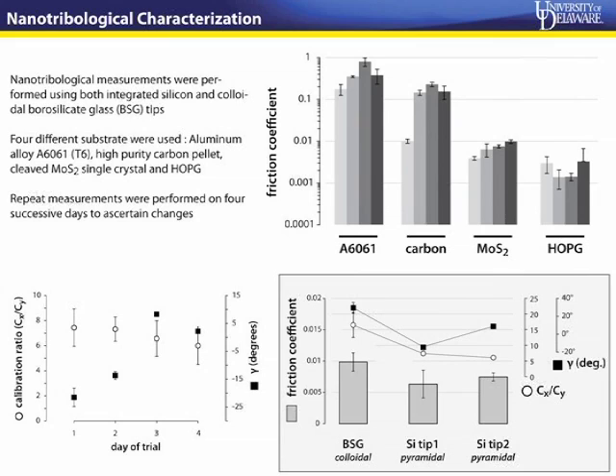Another test that we did was to see if this is applicable to a colloidal probe, because there really isn't any reason why we cannot calibrate levers with colloidal probes also, because we're really scanning on the substrate of interest without any need for a given calibration grating. In this result, these were scans done on MoS2 single crystal, and for pyramidal tips integrated probes, we used 2 silicon probes and 1 borosilicate glass, 14 microns in diameter, colloidal probe.